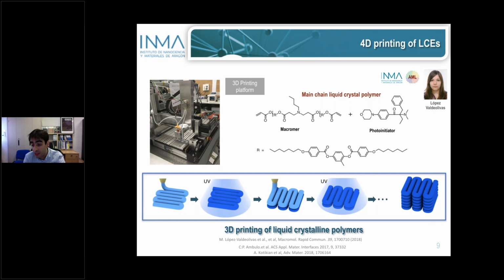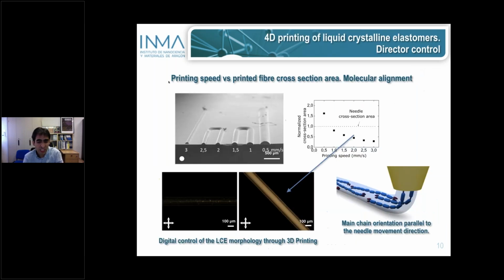We can iterate this, and we can generate several layers. We are using 3D printing, so we can therefore grow into the third dimension. Here you see lines of material printed at different speeds, so they have different cross sections. And what we saw advantageously for us is that, especially for high speed movement of the nozzle, the needle that dispenses the polymer, and this is a key point I want to call attention to, because this is a key point for this technology, we get a preferential orientation of the molecules aligned parallel to the direction of movement of the needle, as you see in the cartoon bottom right part of the slide. And this is the key point, because with this printing platform and this material, we can digitally control the orientation of the molecules in the printed structure.